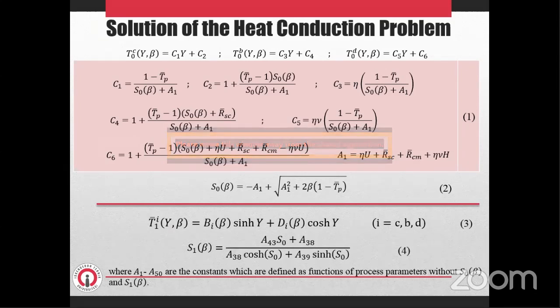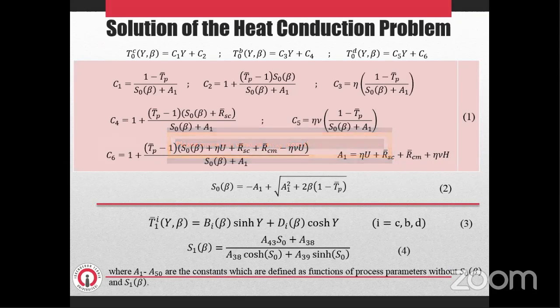Subject to the governing equations for the first order heat conduction differential equations, we assume general solutions for the first order temperature field in the layers as follows, and the coefficients are functions of the other process parameters. Finally, the amplitude of the perturbation on the solidified shell thickness is calculated in equation 4. A1 to A50 are the constants which are defined as functions of process parameters without S0 beta and S1 beta.